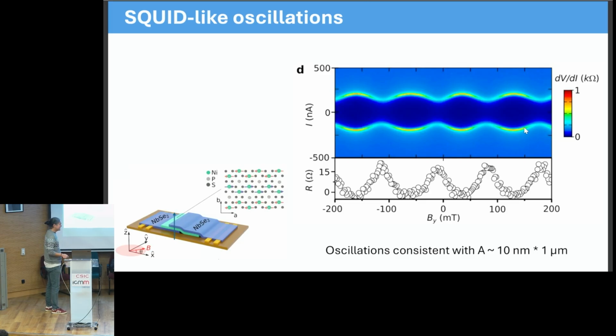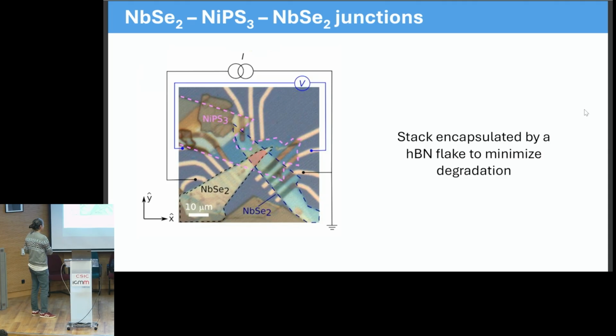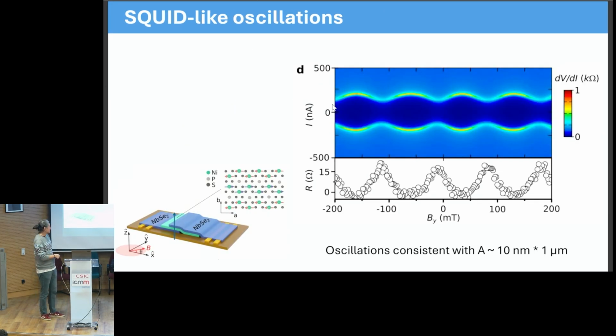Now, the period of the oscillations, as I mentioned before, has some information about the size of the junction. And when we take into account the period of the oscillations and compare to the device, it is consistent with the geometries that we have. So going back to this photo, the junction has a few microns extension laterally, and the thickness is the thickness of the NiPS₃ layer, which will be of the order of 10 nanometers or less. So from the oscillations, we get an area consistent with 10 nanometers thickness and a width of around 1 micron or a bit more. So this seems to fit the dimensions of our device, but it shows SQUID oscillations instead of what we would expect, perhaps a Fraunhofer.